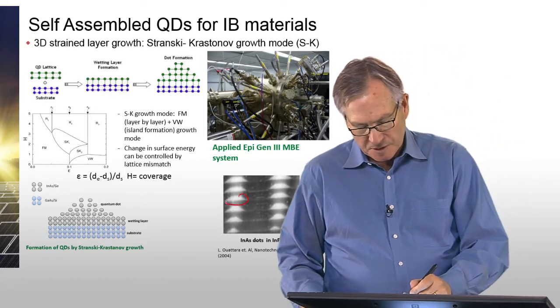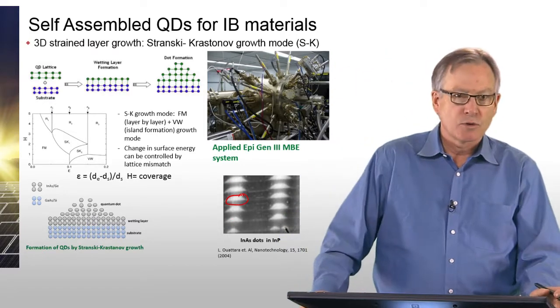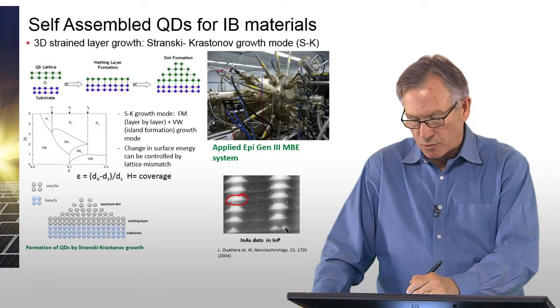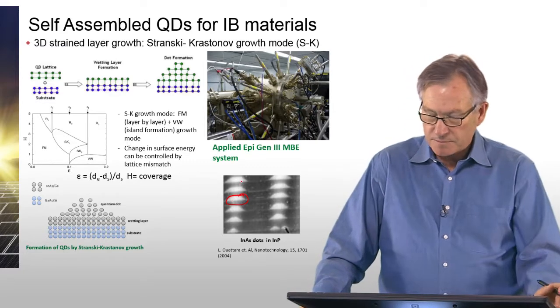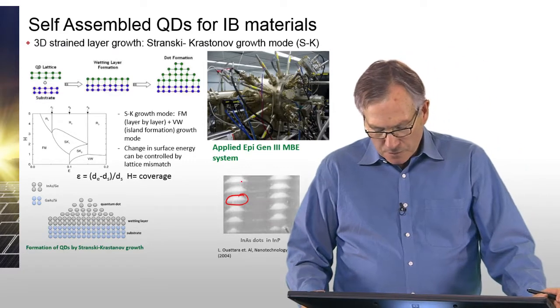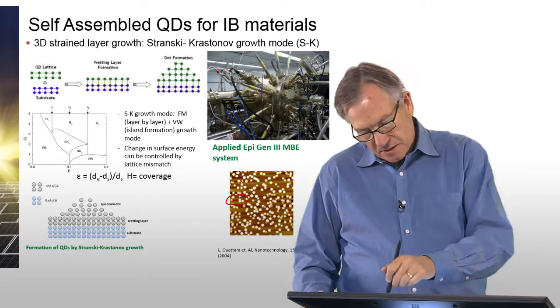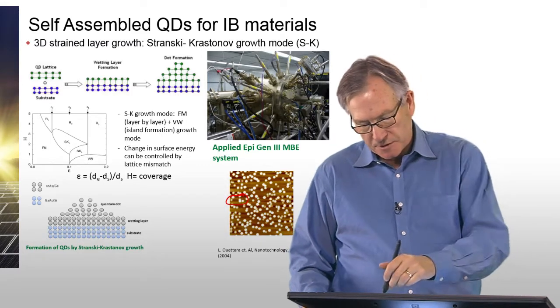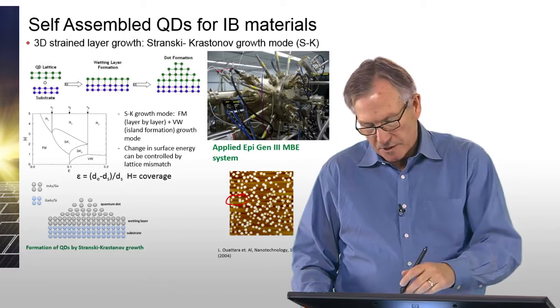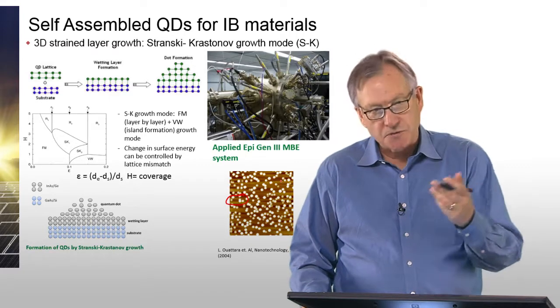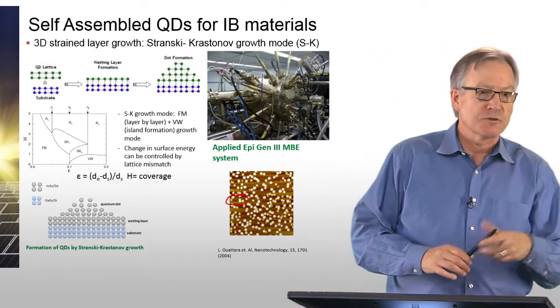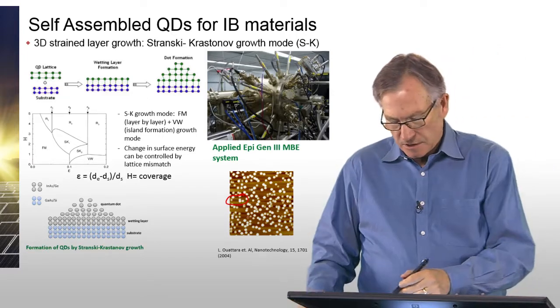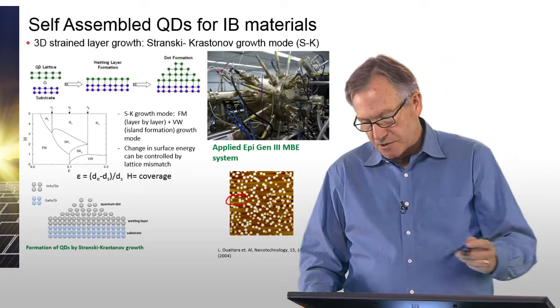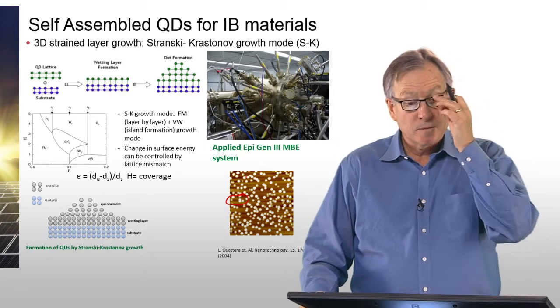So what's shown here is basically an individual quantum dot grown by this method. This is an indium arsenide quantum dot embedded in indium phosphide. From a top view, what you see is that these are random in the sense of their location with respect to one another. You can see that the size is relatively uniform, which makes this useful. The size of these individual quantum dots is fairly uniform.